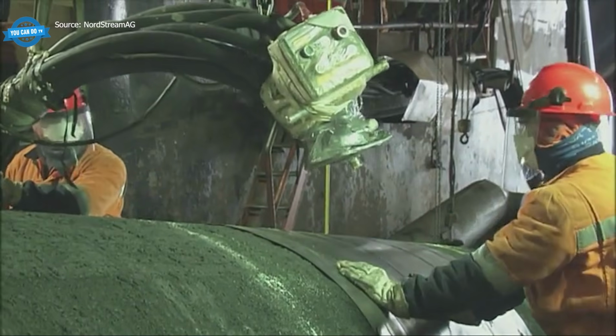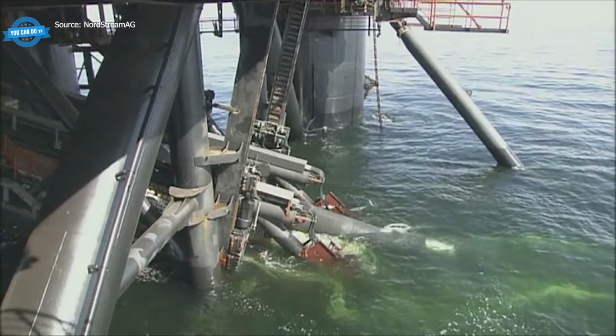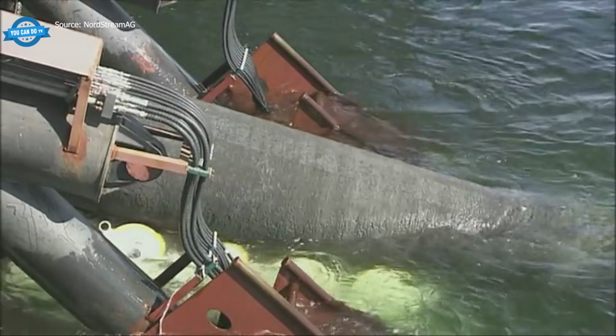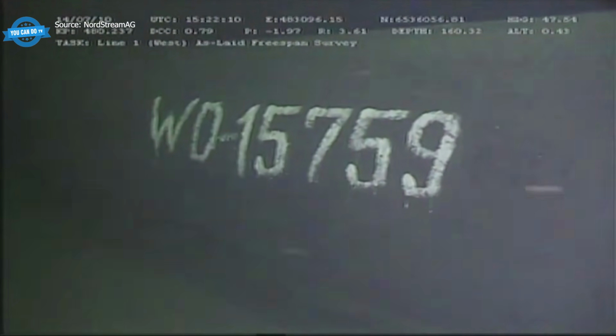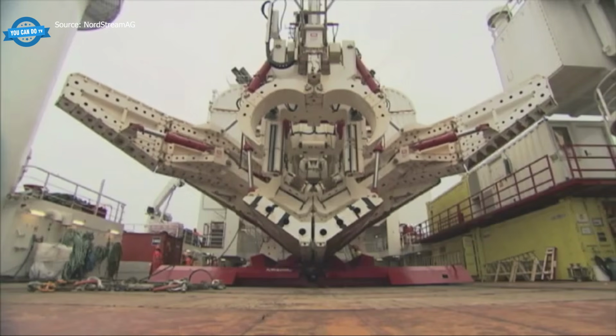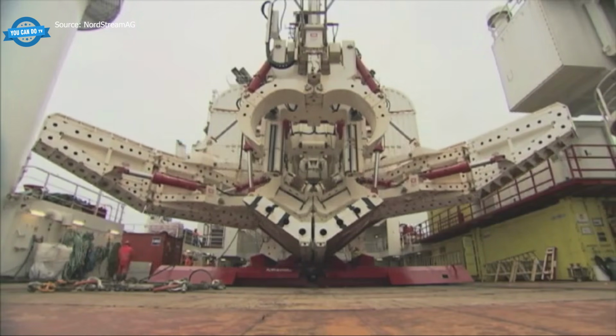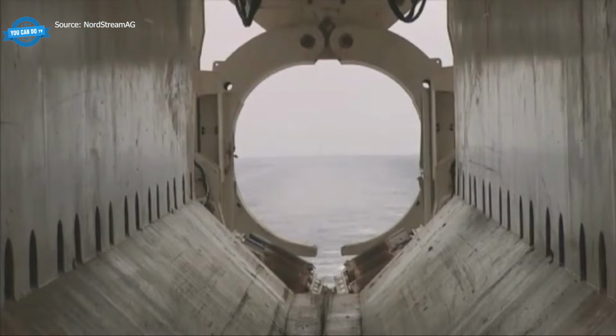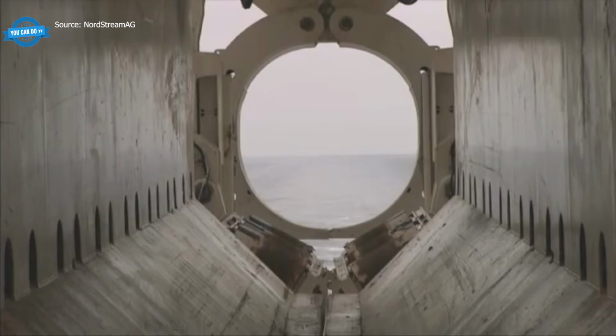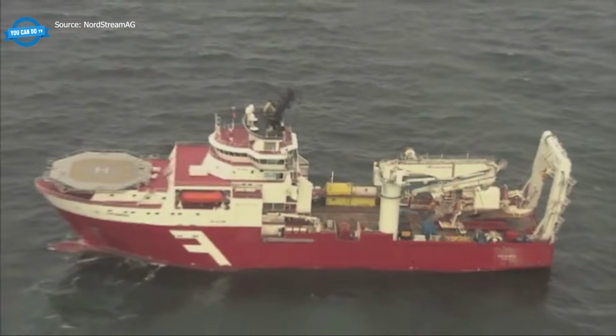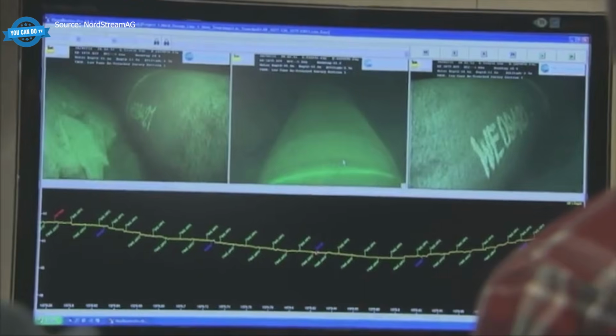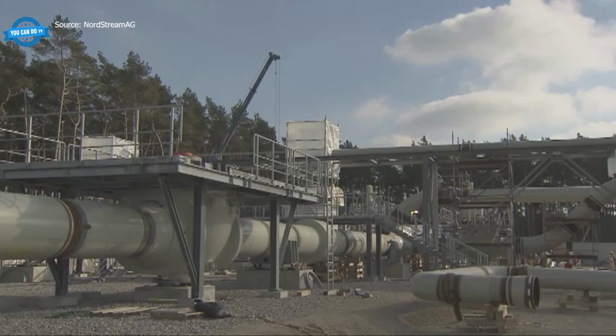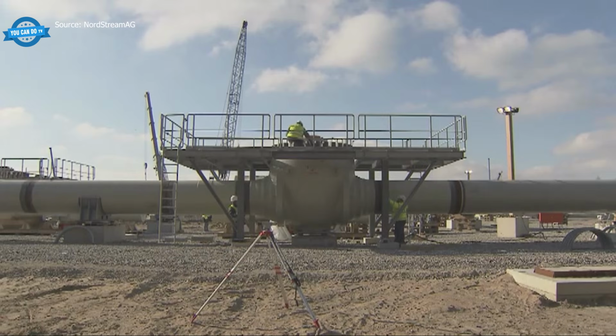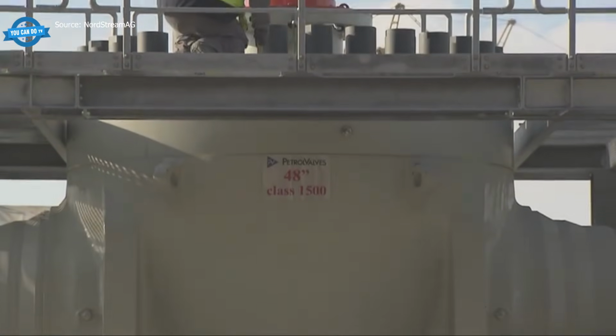To survive any of this, each pipe is built with high-grade steel specified for external pressure and wrapped in a concrete coating that adds enough weight to keep the line pinned to the bottom. Every weld goes through ultrasonic non-destructive inspection before the joint is sealed with a corrosion-resistant heat-shrink sleeve and polyurethane foam. Where protection is needed, a dedicated subsea plow cuts a trench so the pipe can be lowered below the seabed instead of remaining exposed on top of it.